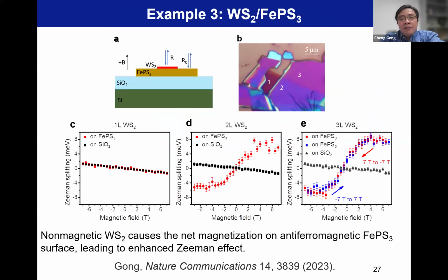The third one is even more exotic. I have a 2D anti-ferromagnetic layered material, iron phosphor sulfide, and I put one layer, two layer and three layer tungsten sulfide, which is non-magnetic. And I use a circularly polarized white light and see the absorption dip. So that probes the spin polarized band gap of tungsten sulfide.